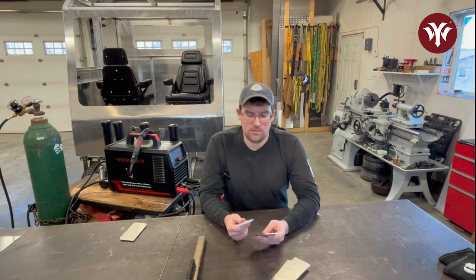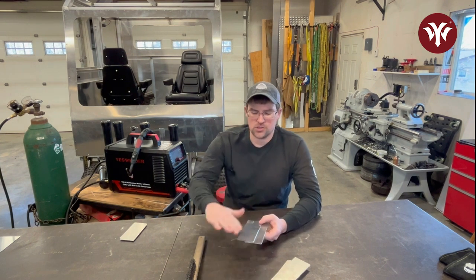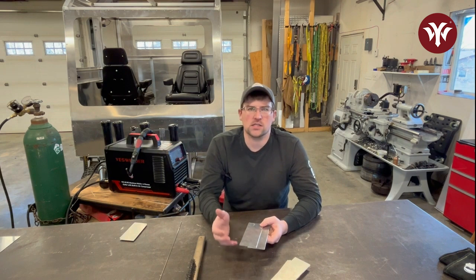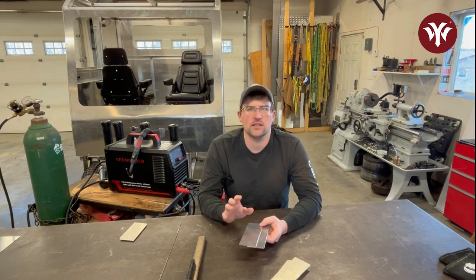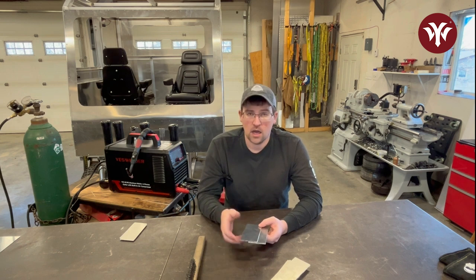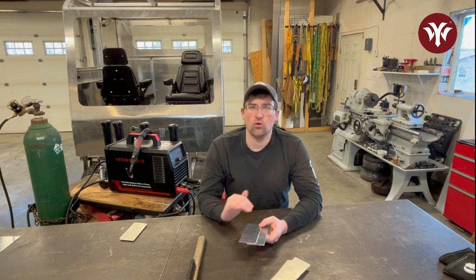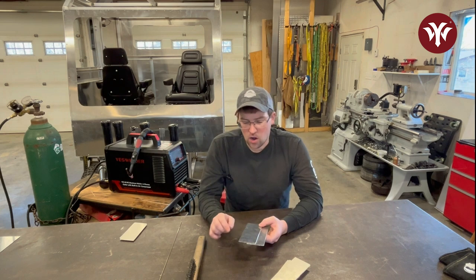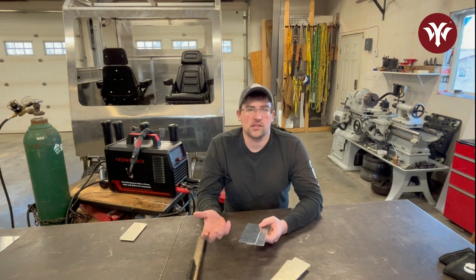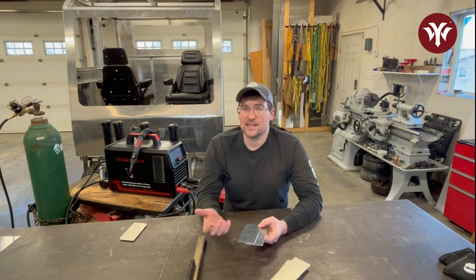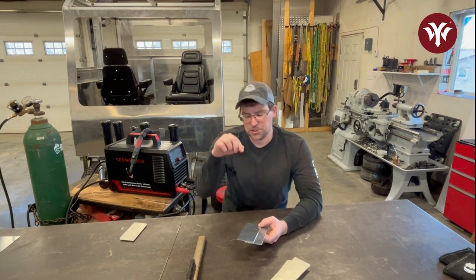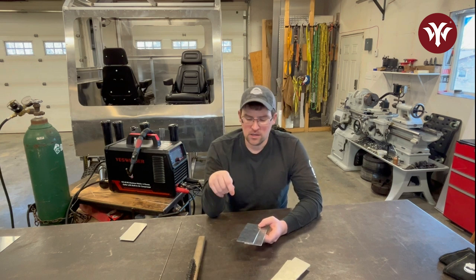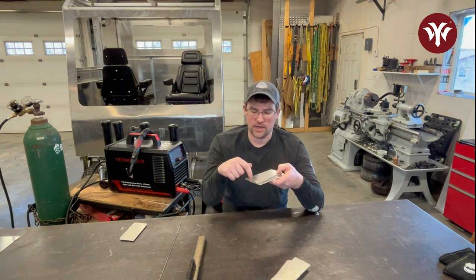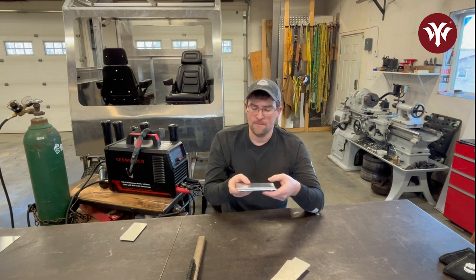There's an interesting part about aluminum, which is that the surface of the aluminum develops an oxide layer, and this is what is going to fight us the most. Just like steel rusts or oxidizes, aluminum builds an oxide layer as well over time. That oxide layer is causing us so much problem because it melts at a significantly higher temperature than the base metal itself. So you can imagine striking an arc on here and trying to develop a nice little molten puddle that you can feed rod into.